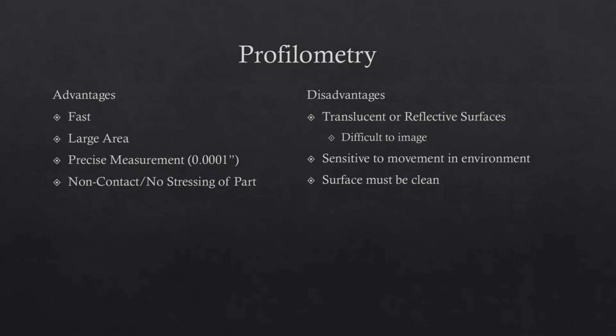If you have translucent or reflective surfaces, they're difficult to image. Just like heat reflective surfaces are difficult to image with a thermographic camera. It's kind of the same thing. It is sensitive to movement in the environment. That was our biggest problem.